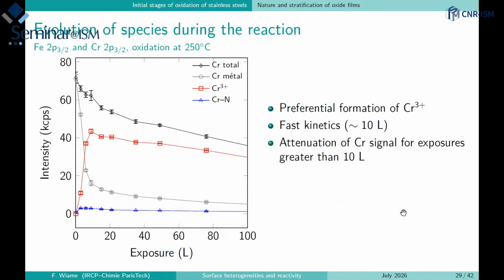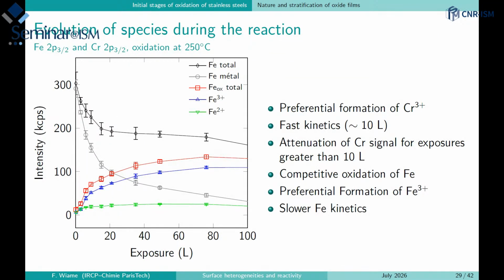If we are looking at the evolution as a function of the exposure, we can see that in the case of chromium, we have a very fast decrease of the metal component, which is associated with the growth of the oxide, which is also very fast. You see that in a few Langmuir, we have already a very high amount of chromium oxide, which is what we want, because this is the chromium oxide which is passivating the material. So we hope that we will have a fast increasing chromium oxide layer. But you can also see that after some time, the chromium intensity is decreasing. In fact, this is due to the fact that some iron oxide is growing on top and attenuates the signal of the chromium oxide. And there is a competitive growth with iron oxide, which starts slowly, but in fact continues for quite a long time.